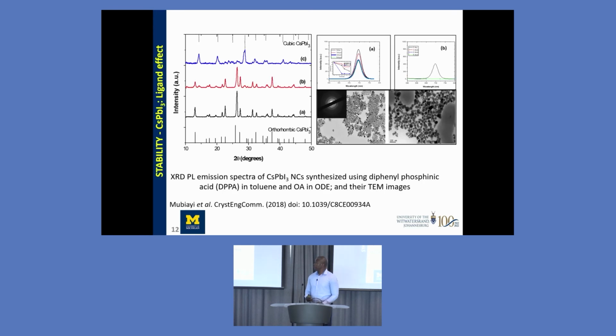So specifically here, I wanted to show you the stability of nanocrystals. Here we use cesium lead iodide. One can ask, why are you using lead? Okay, we use cesium lead iodide as a reference because it has been widely studied. And we know that many of the researchers are reluctant to continue with lead due to the environmental effects besides the stability. So we use it as a reference just to see if we can improve the stability.